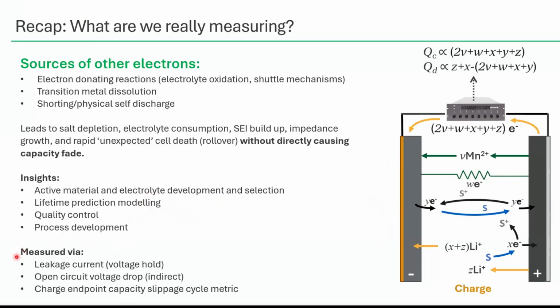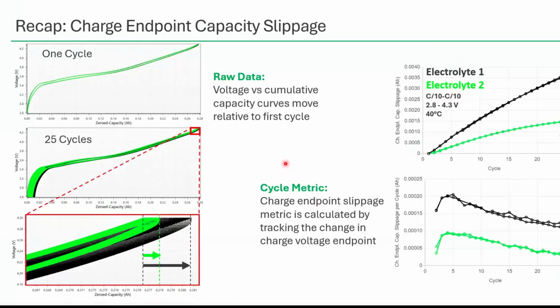And we can measure these things a few different ways, and I'll show a few of them in this webinar. Leakage current, just direct measurements of say, these shuttling mechanisms happening. Open circuit voltage drop, which is more of a traditional way of measuring some of this, the self-discharge occurring. And then charge endpoint capacity slippage as a cycle metric, which is typically not used very much or talked about, because it is really only possible with ultra high precision equipment. I'll just show this for reference.